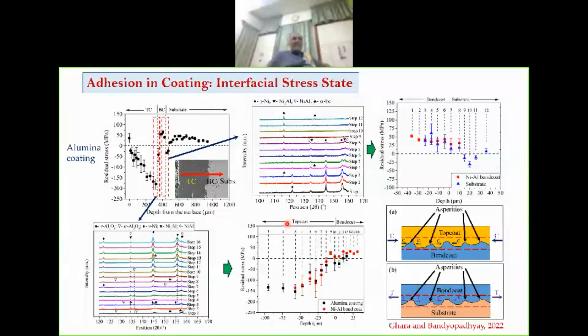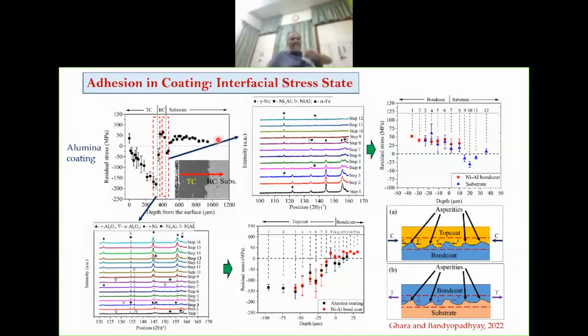We measure the residual stress profile of the coating. We start from the top coat, get into the bond coat and slowly get into the substrate. We get near zero stress at the top coat and we gradually go inside and get a strong negative compressive stress. When we come to the bond coat, we get low compressive followed by low tensile stress. In the substrate, we have low compressive to low tensile. This is a bit intriguing.